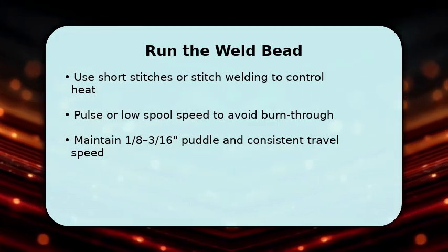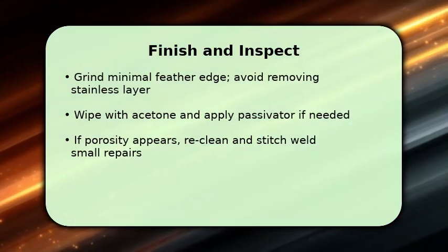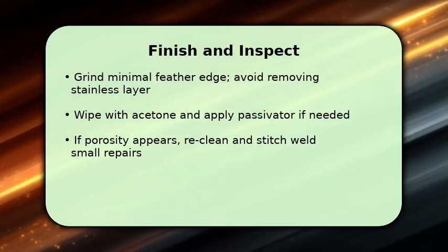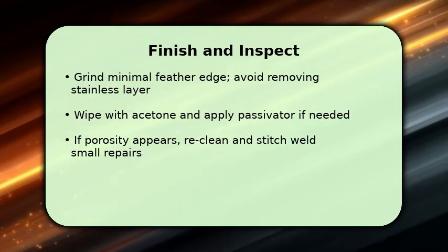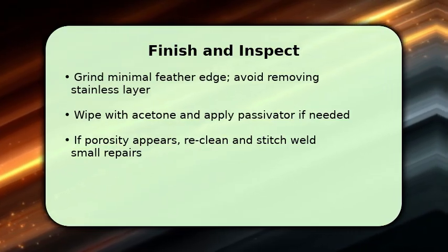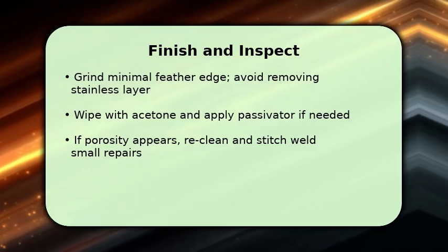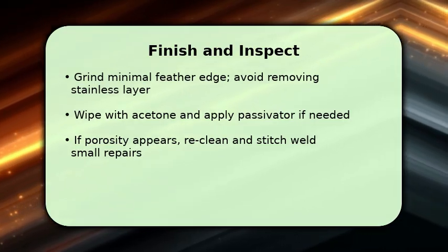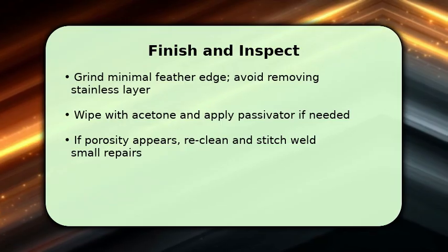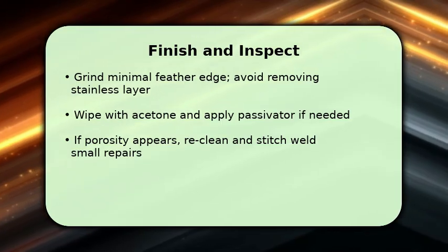You finish by blending welds carefully. Use a fine flap disc to feather edges without overgrinding the stainless. Once done, degrease the area with acetone and apply a passivation solution to restore corrosion resistance if the surface was heated heavily. Inspect inside for leaks by pressure testing.